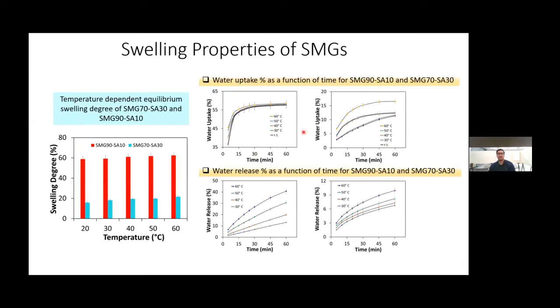Here are the swelling properties of the shape-memory hydrogel materials. We found a 60% swelling degree for SMG 90 SA10 and a 20% swelling degree for SMG 70 SA30, where the crystalline concentration is higher. This 40% difference actually enables the actuation. We also observed the water uptake percentage and water release percentage, and you can see that most of the water uptake happened within 15 to 20 minutes.